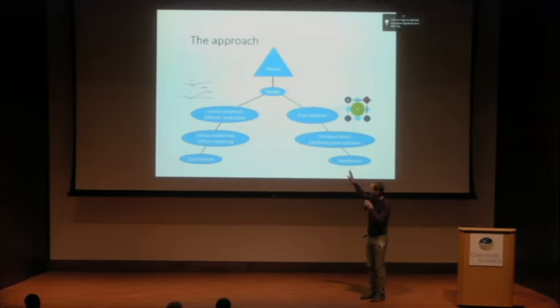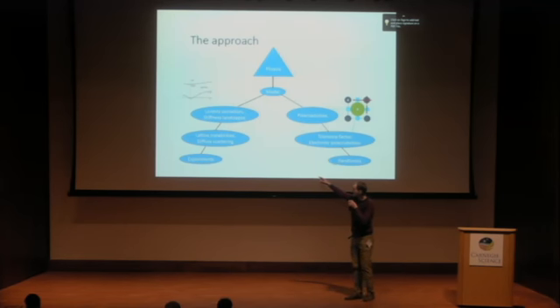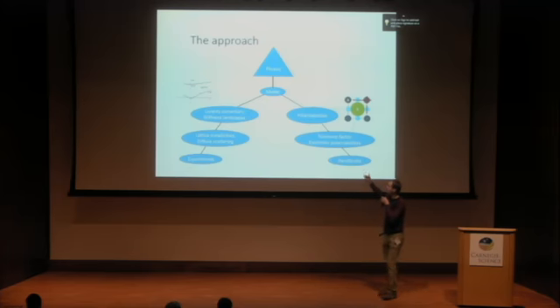So we want to understand physics, and we should bring up the model that gives us the Lorentz correction. Due to this Lorentz correction, everything is linked to the experiments, to lattice instabilities that we observe, or to diffuse scattering that we measure. On the other hand, the model has parameters, and these parameters are polarizabilities. When we compute the Lorentz correction, it should be like that in the simplest case. And then these parameters we can link to the tolerance factor, to electronic polarizabilities, and in the end to the values that are tabulated in the handbooks, let's say ionic radii and polarizabilities.